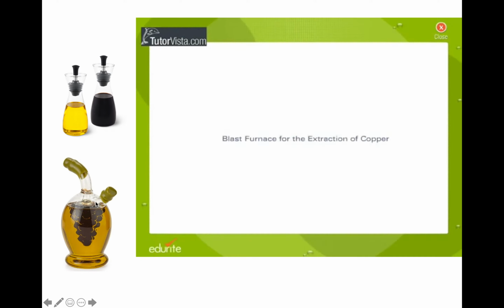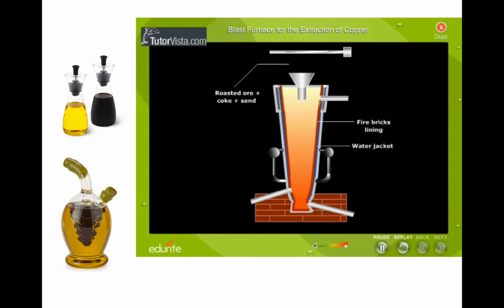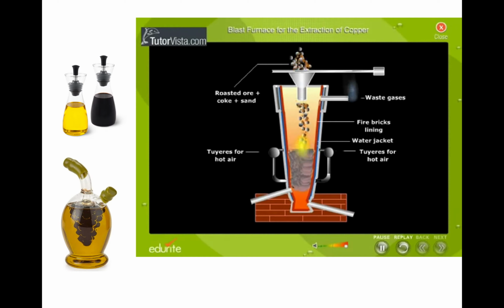Blast furnace for the extraction of copper. A mixture of roasted ore, sand, and coke is dropped into the furnace and heated. Simultaneously, a hot blast of air is pumped in through the tuyeres. Ferrous sulfide, the impurity, forms a fusible slag of ferrous silicate. The molten slag floats on copper sulfide that can be tapped off through the outlet. Matte, consisting of copper sulfide and traces of ferrous sulfide, sinks to the bottom and is tapped off through the lowermost outlet. Waste gases are let out through an outlet at the top.